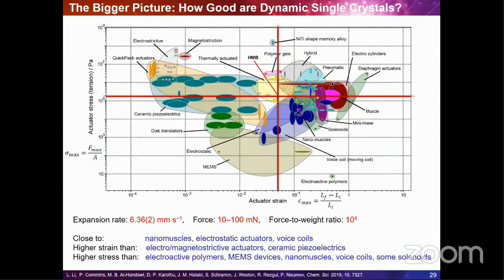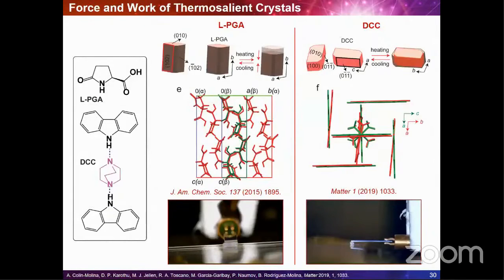So our intention is to establish these kinds of global performance indices to be able to assess how good these crystals are. In fact, a systematic study on a larger data set, using selected performance indices that are common in materials engineering practice, is really required at this point to be able to realistically and thoroughly assess their performance. So we went on further to set general performance metrics that can be used for quantification of the performance of these prospective dynamic materials. The indices were calculated on two selected representatives of thermosalient solids, which are shown here. One of them is pyroglutamic acid, the other one is a co-crystal between two molecules.